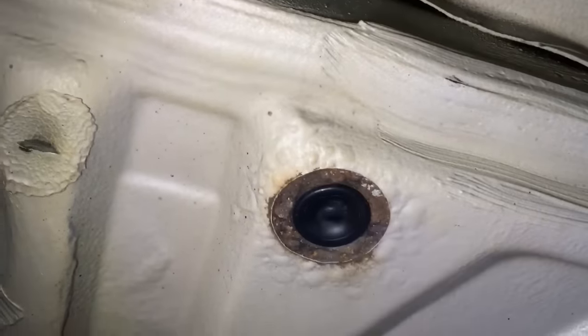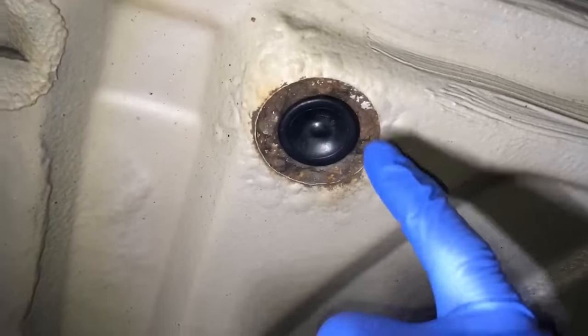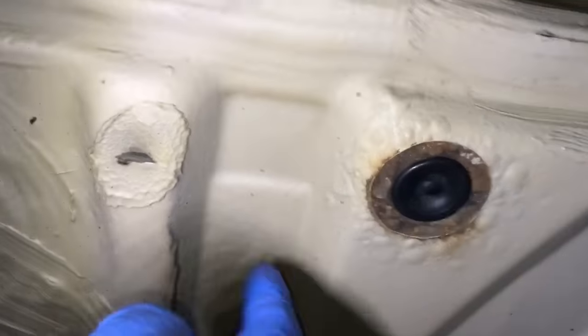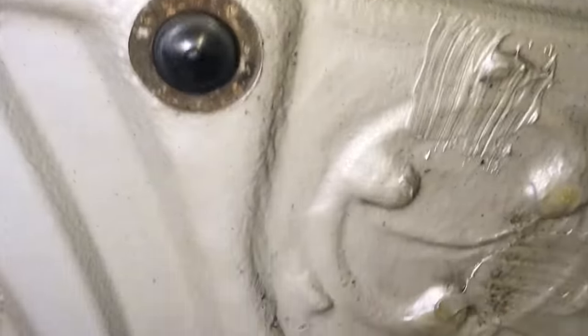So where the grommet is applied at both rear corners, we can see that it's corroded on the metal edge, but also underneath the seam sealer, it's bubbled with pimples. That's corrosion under there. So if we touch that, it will just start growing and growing. So that'll be a large area of seam sealer we need to take out. Got the same on the other side as well, so that needs dealing with. I think that is about it, really. Central sections look fairly good.